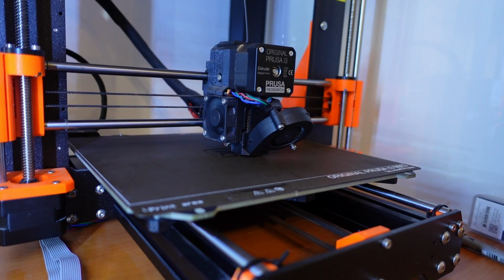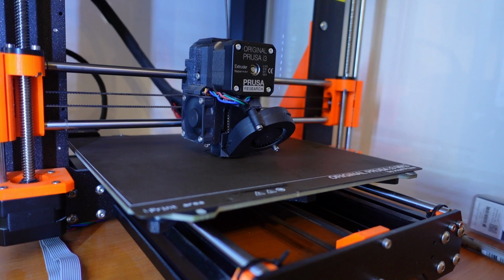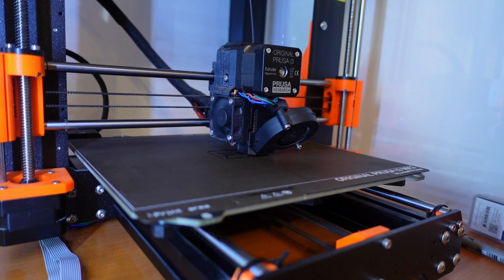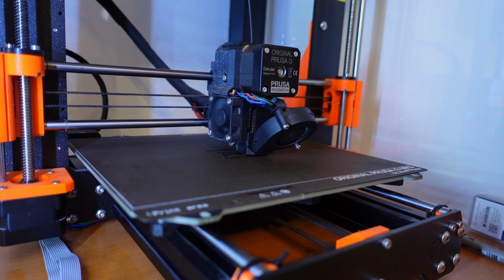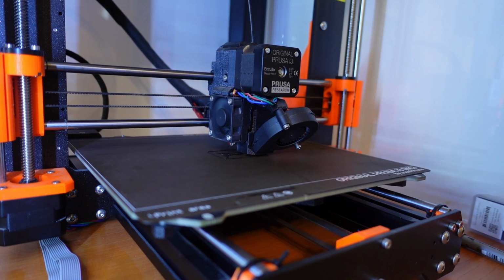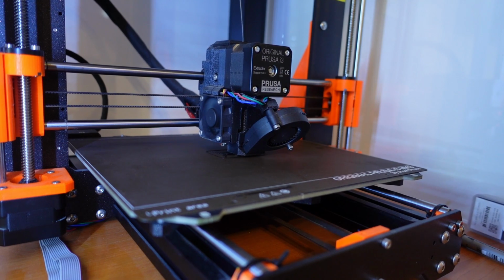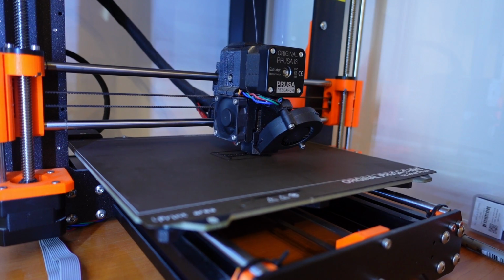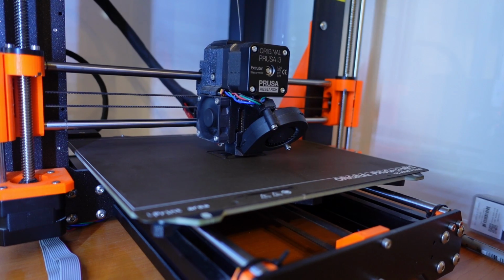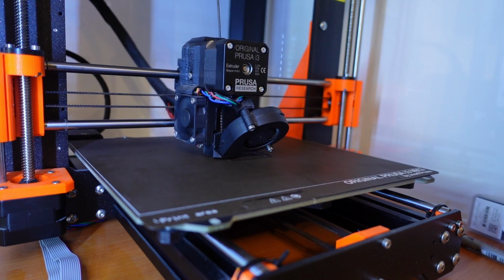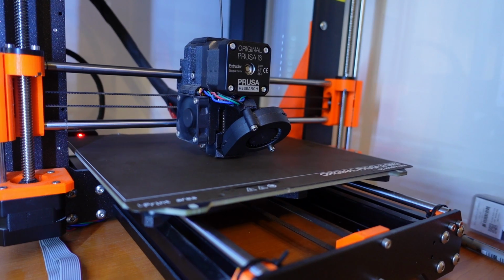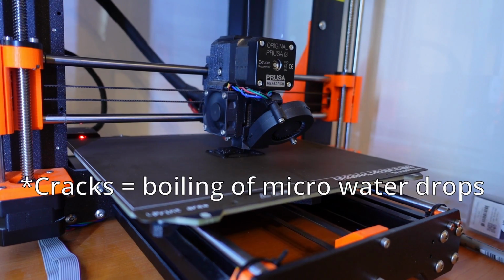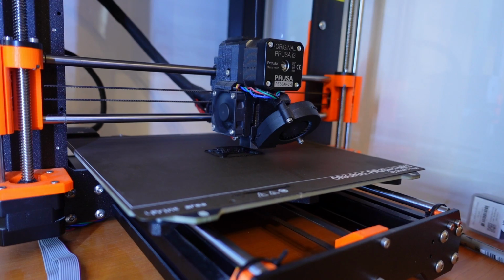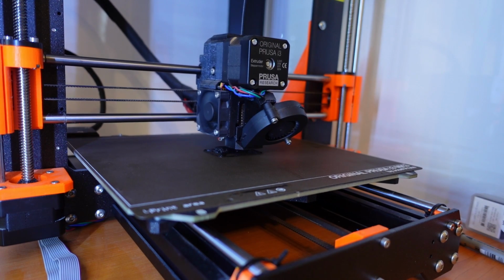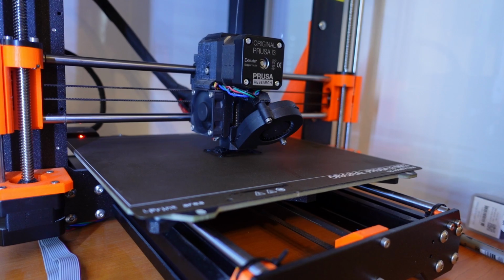It's a little bit hard to see, but the start is good. I'm expecting a little bit more stringing here because this is 0.6 millimeter nozzle and the TPU filament. I left the default 0.8 millimeter retraction length, but we will see if it is enough. This is satin Prusa sheet, and the temperature on the bed surface is 40 degrees Celsius, and I believe this will be enough. I can hear some cracks from time to time, so this means that this is not completely dry filament. Well, the TPU absorbs moisture, and it is almost more than 1 year old filament, so probably I should dry it before I continue using it.